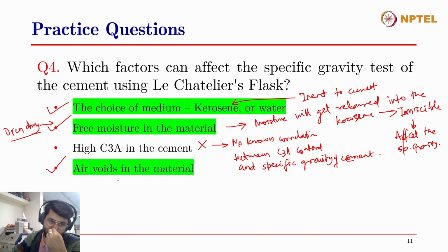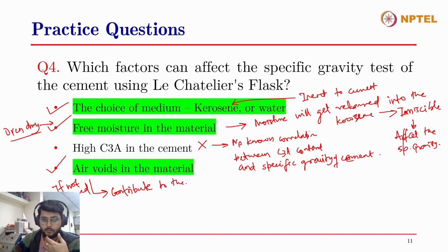The final one is air voids in the material. Yes, of course, when the cement is in its anhydrous state, when you take it out from a cement bag, it will have air voids within the solids. And when we put it in the Le Chatelier's flask in the kerosene, we need to remove these air voids that are entrapped within the flocks or within the solids, because that will contribute to the volume measurement. If the air voids are not released, they will contribute to the volume calculations, and hence specific gravity will be affected.